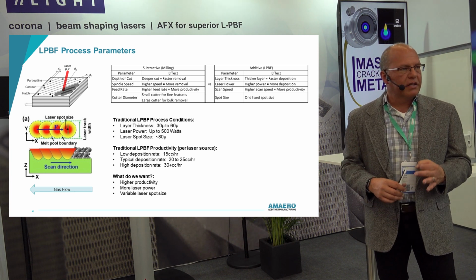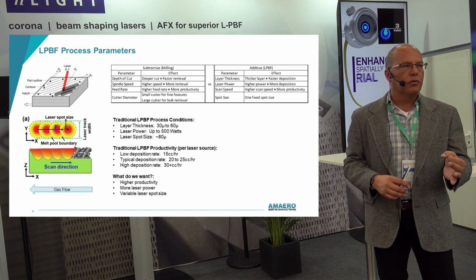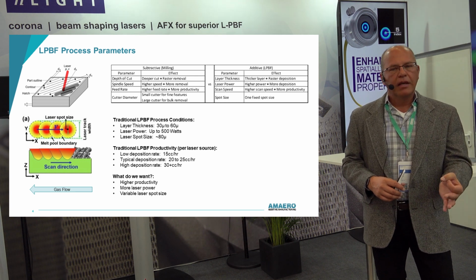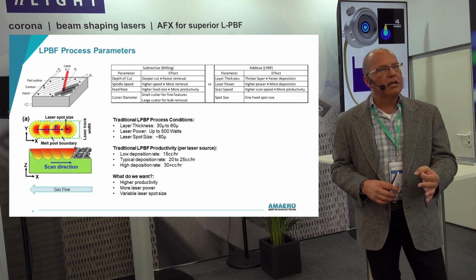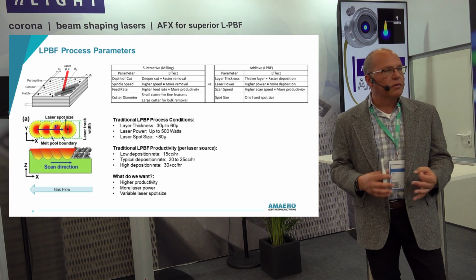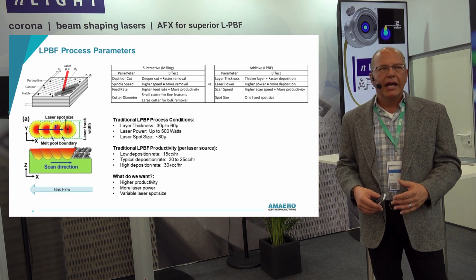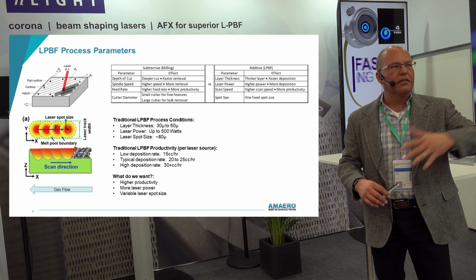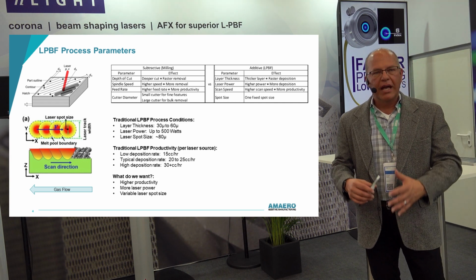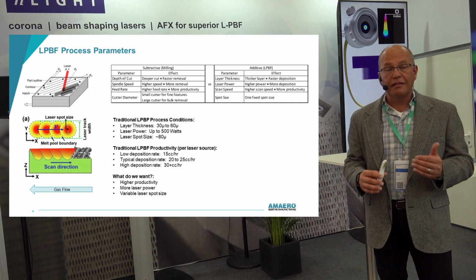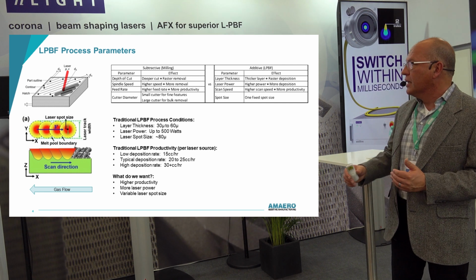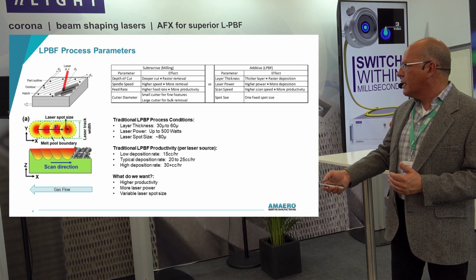It's a good compromise size because it lets us contour with good surface finish, and it lets us print details of pretty good feature resolution down to about 0.5 millimeter, and it's okay about filling in all the bulk. But having just one spot size that does not fit all applications is a challenge.